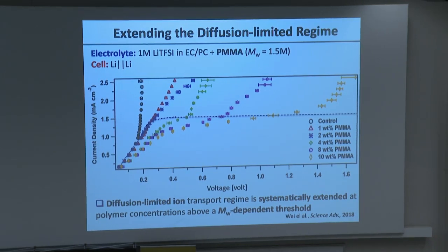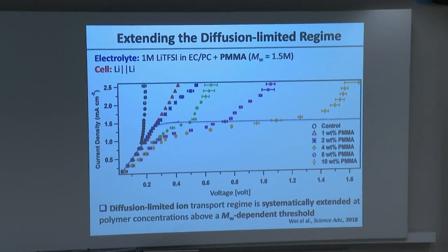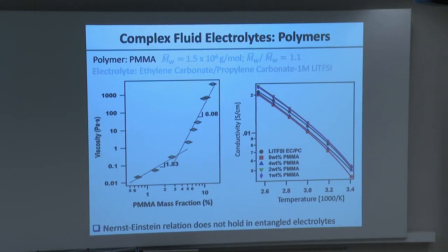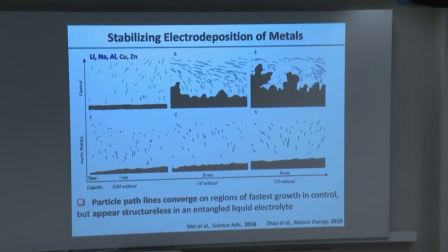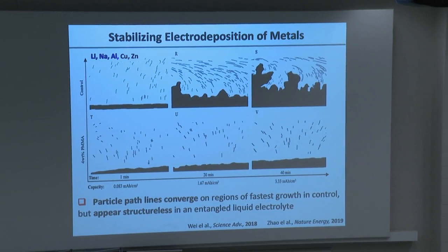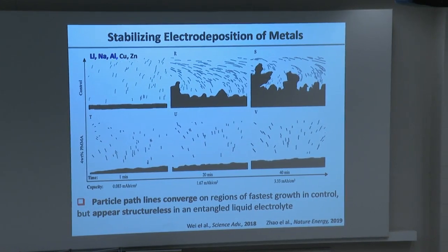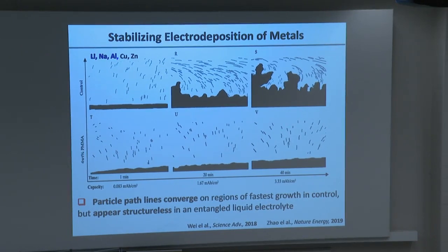Where I started, though, was can I stop the instability which produces the dendrites from occurring? I'll skip that. And the answer is, my goodness, yes, okay? So the student who did this was actually a very interesting student. She wasn't interested to just do it for lithium. What we're doing, again, is plotting how the tracer particles move, which I showed you earlier, but also looking at how the interface grows. In the top, this is the absence of polymer. In the bottom is when we add the polymer. So in the top, what you notice is that, first of all, the bumps grow in a random way, so they begin to become dendritic. And as I deposit more, the bumps grow even more.